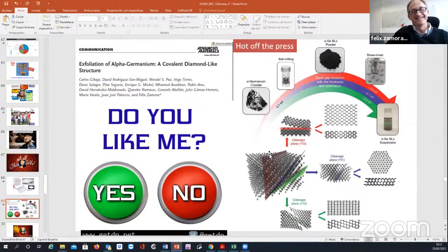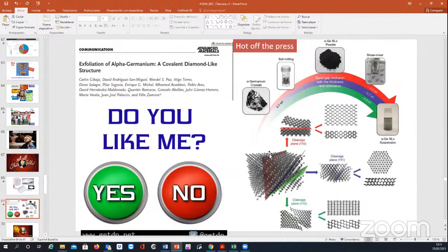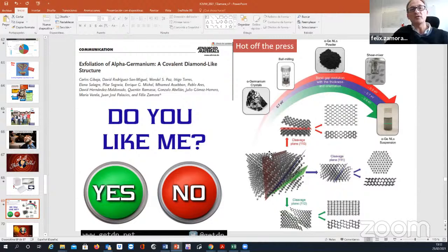Because this is not a layered material, I can imagine that the bonding energy or the bonding density can make a difference. That you can probably break some bonds. Exactly. We calculated, in collaboration with Juanjo Palacios, the different energies along the several cleavage planes, and this makes the difference, of course.